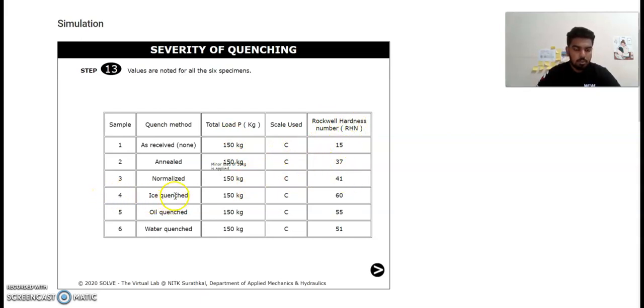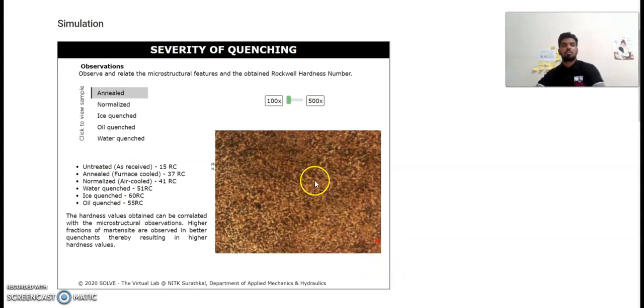Sample 4, ice quench, total load is 150 kg, scale used is C, Rockwell hardness number is 60. Sample 5, oil quench, total load is 150 kg, scale used C, Rockwell hardness number is 55. Sample 6 is water quench, total load is 150 kg, scale used is C, Rockwell hardness number is 51.